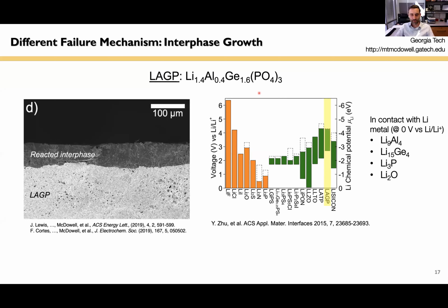This is from some previous experiments where we were investigating a different solid electrolyte material. This is an oxide material, LAGP, lithium aluminum germanium phosphate. It's a NASICON type ion conductor. It has slightly lower conductivity than the sulfides I was just showing, but it was quite useful for these experiments. In these experiments, we were investigating what happens at the interface when you contact lithium metal to this solid electrolyte material. Thermodynamically, based on calculations like this, you expect a bunch of binary phases to form. With this material, you might expect lithium aluminum and lithium germanium phases to form, as well as the phosphide and oxide phases. When we started this work a few years ago, we didn't really know if these binary phases would form or not. Thermodynamically, they're expected, but there's also kinetics aspects that are important. And so we decided to investigate these details with a variety of different experiments.